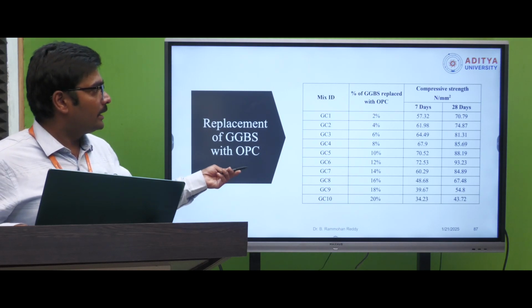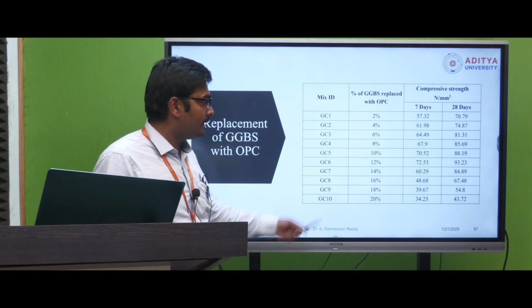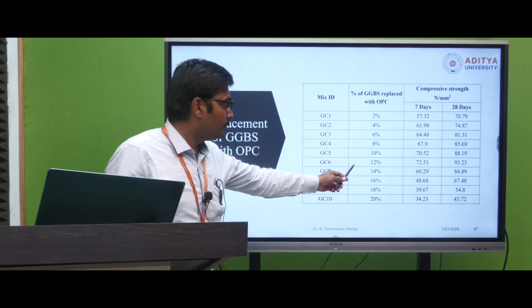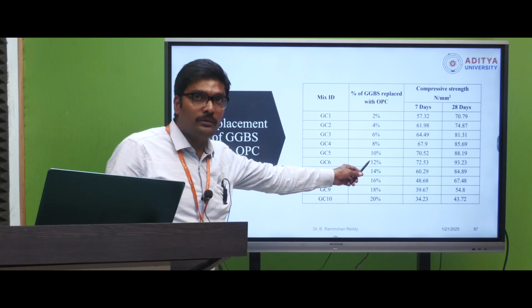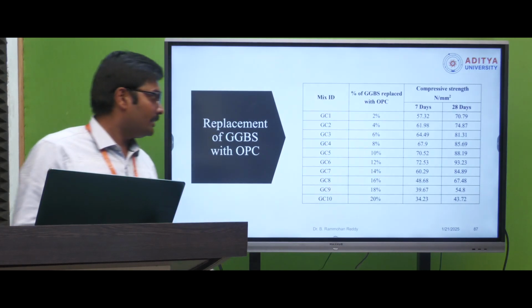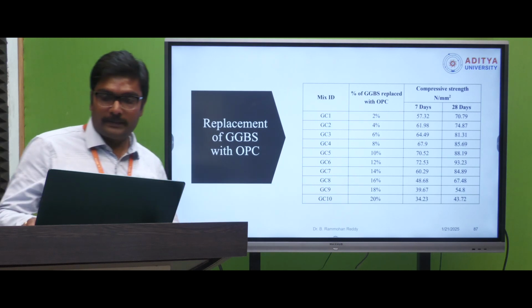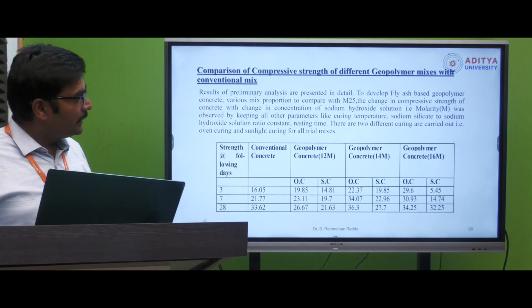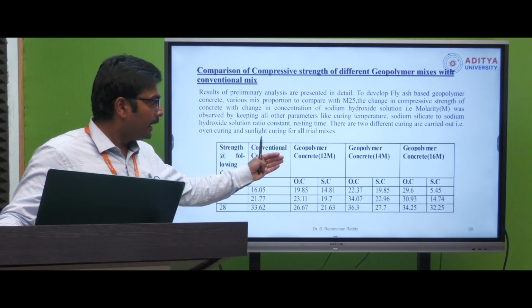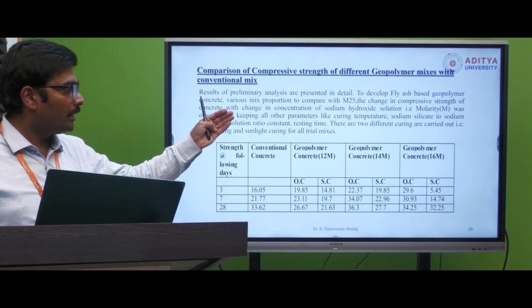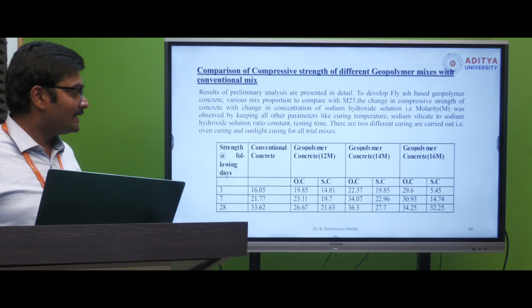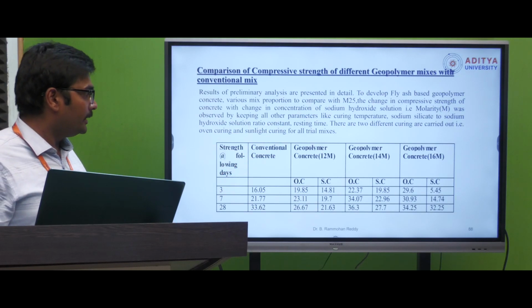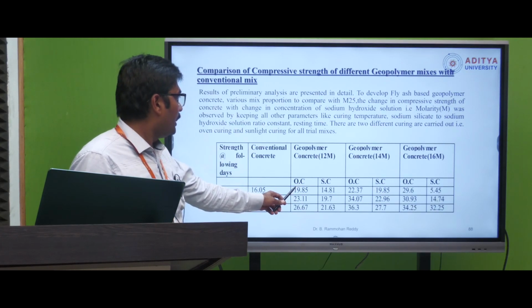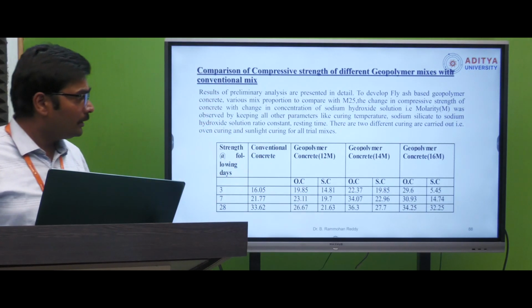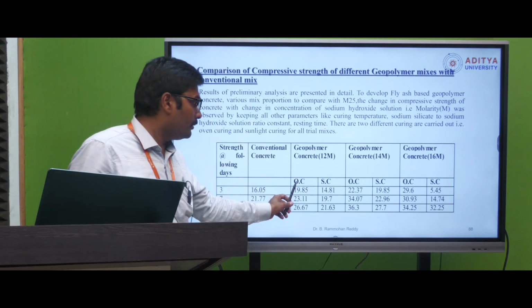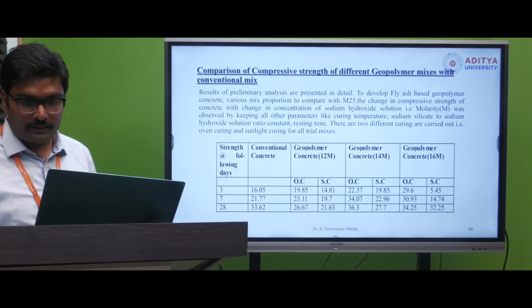Similarly, another attempt he made was replacing GGBS with OPC. Similarly, a 12% replacement of GGBS with OPC gave better compressive strength results, that is the GC6 mix. Similarly, one author presented geopolymer concrete at different molarities, 12 molar, 14 molar and 16 molar NaOH solution, and also at different curing conditions like oven curing and sunlight curing. He presented that, compared to sunlight curing, oven curing gave better compressive strength results.